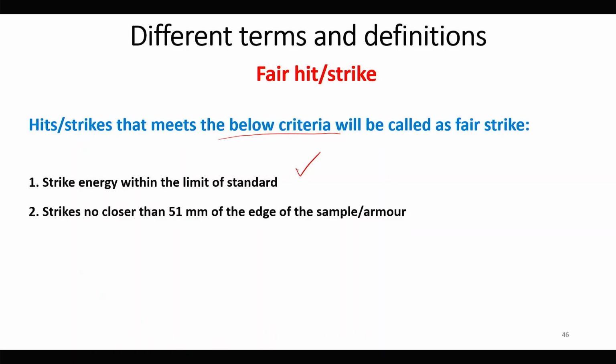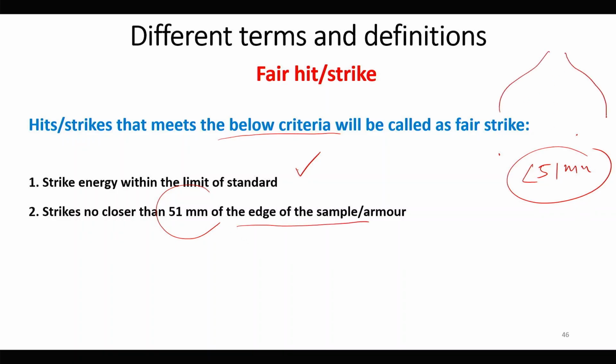And the distance between the strike and the edge of the sample should not be less than 51 millimeter. So, if the sample is there, the strike should be more than 51 millimeter from the edge.